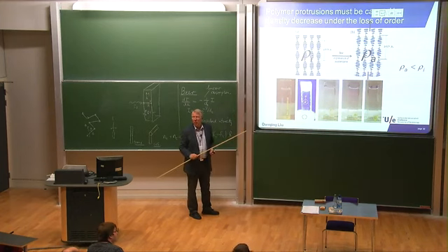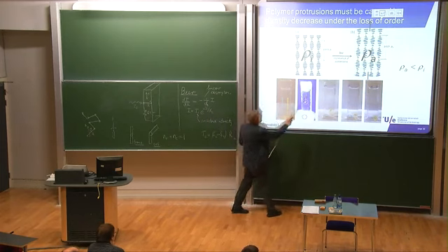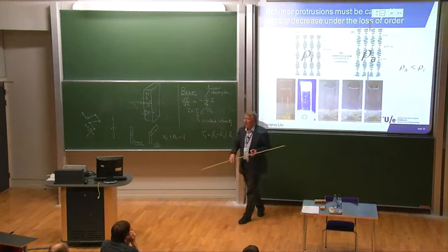Then you expose this film with light, and because the density decrease occurs during exposure, this film with the azobenzene starts to float. Not surprisingly, for reference, the tinuvin sample remains at the bottom. So it's again not a real heat effect which is dominating here. And then you stop exposing, and nicely the azobenzene sample starts to sink to the bottom again.